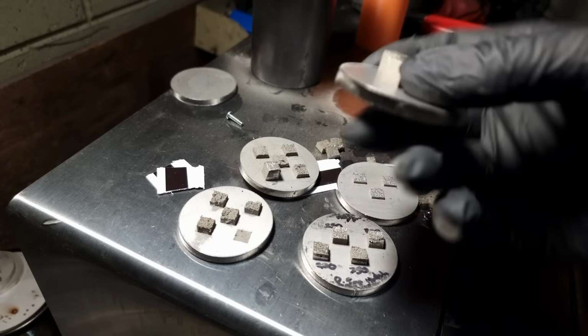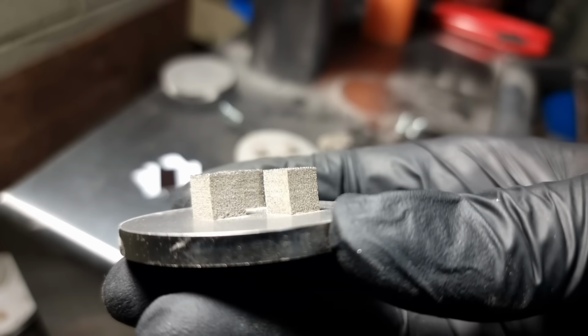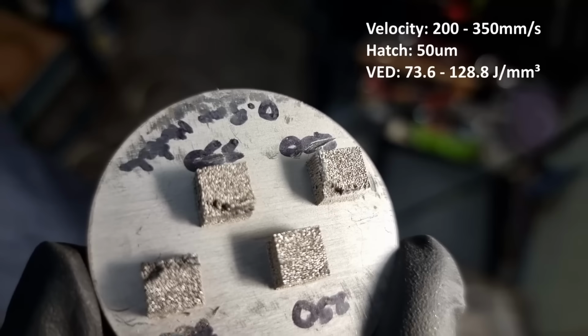The next few runs would focus on dialing in the settings, as a lack of fusion was still undermining part strength. The most obvious answer to this was to increase the input energy, and seeking to minimise the potential for spatter, I would do so by reducing the hatch spacing. I dropped the hatch spacing down to 50 micrometers and started to search for a print speed that would grant me enough part strength without compromising too much elsewhere.